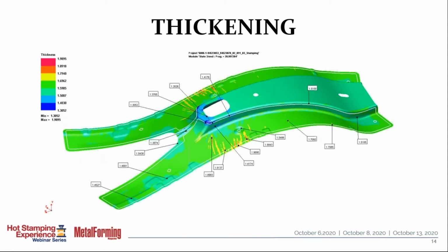Thickening is generally the bigger issue, and so we always are concerned about that. The metal tends to stick and bunch up, so in the event that we can't control the thickening, we get too much thickening, then we may have to use a different pad strategy. Instead of putting a pad over this area to control it, we might put pads on the outside and to allow us to control the wrinkle heights out in this area during forming.